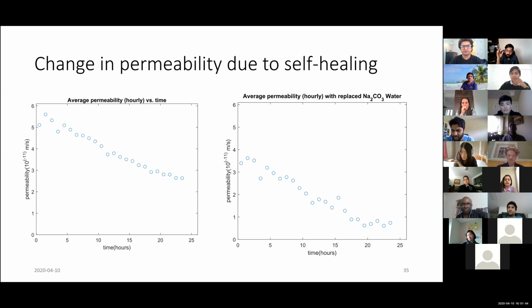Probably there is no easy way to measure the concentration of sodium carbonate over periods of time, to see if any amount is getting used up. The concentration should really be going down if it's reacting inside the concrete. But probably compared to the volume that is being used up, the volume of the pond is very, very large. Yeah, it's large. I submerge the samples inside, so it's larger than the volume that's being used.